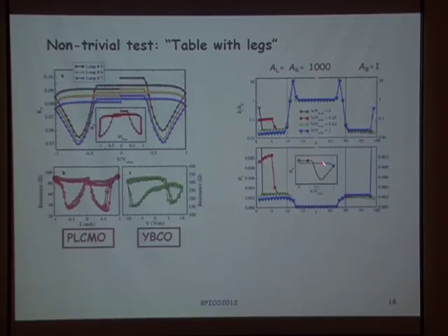So from each of these voltages, we can correlate the high resistance state with this value, and as we increase the voltage, the transition from the high to the low resistance state is correlated with this decrease in the oxygen vacancy content at this interface and this interface.